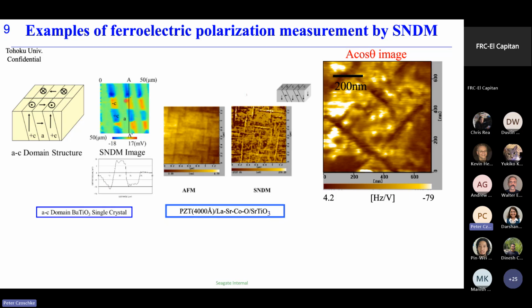And if the tip is on the negative C domain, the SNDM signal is positive. But if the tip is on the A domain, the signal becomes 0. This means that if the tip is on the A domain, there is a crystal symmetry along the depth direction. This means that there is no odd rank tensor component along this depth direction because it has a crystal symmetry. So if the tip is on the A domain, the signal becomes 0.